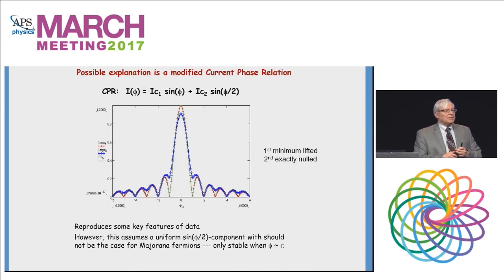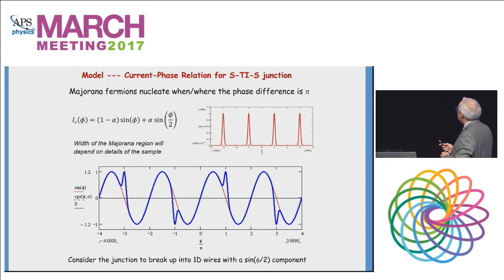So this is appealing to us because it indicates that, one way to get this would be to have a sine phi over 2 term, because in order to get a node, you have to cancel out both of those terms. This is not a very realistic model to have a uniform sine phi over 2, because we really only have Majoranas at various fixed locations in the junction. So a better picture is to think about a complicated order parameter, which has a term in sine phi over 2 at discrete phases in the junction. And so the overall current phase relation looks like this, and notice that it is 4 pi periodic.